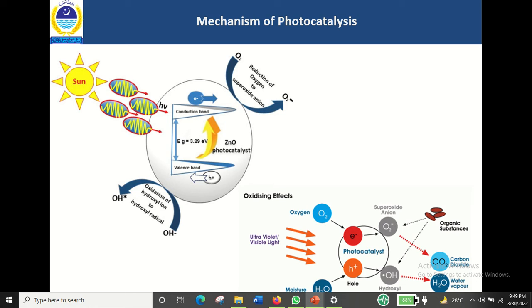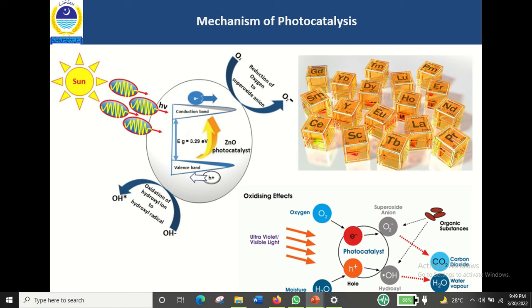So these issues can be addressed by incorporating some suitable dopants, especially rare earth oxides and lanthanum in particular, and by adding some carbonaceous products, for example, carbon nanotubes. Rare earth metals are recognized for their large surface area and high charge carrier trapping ability, which can greatly reduce the recombination of electron-hole pairs.